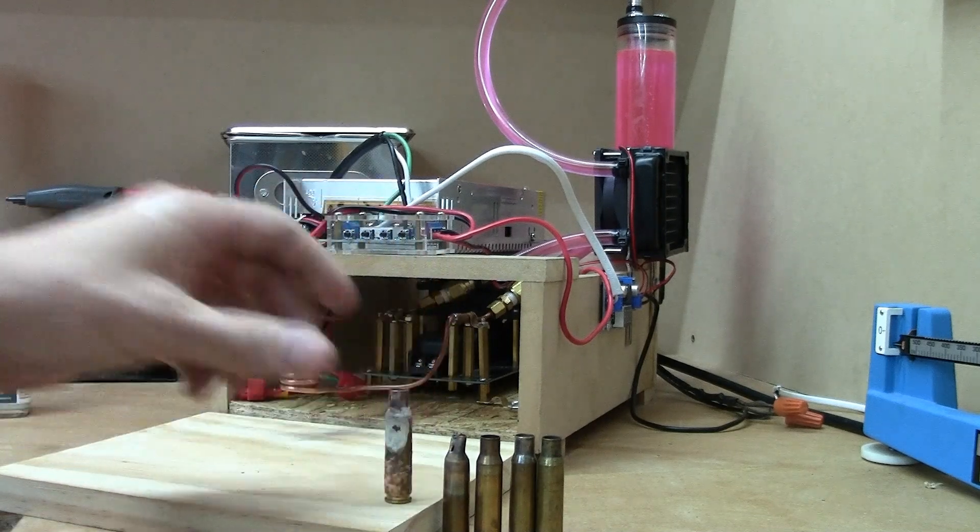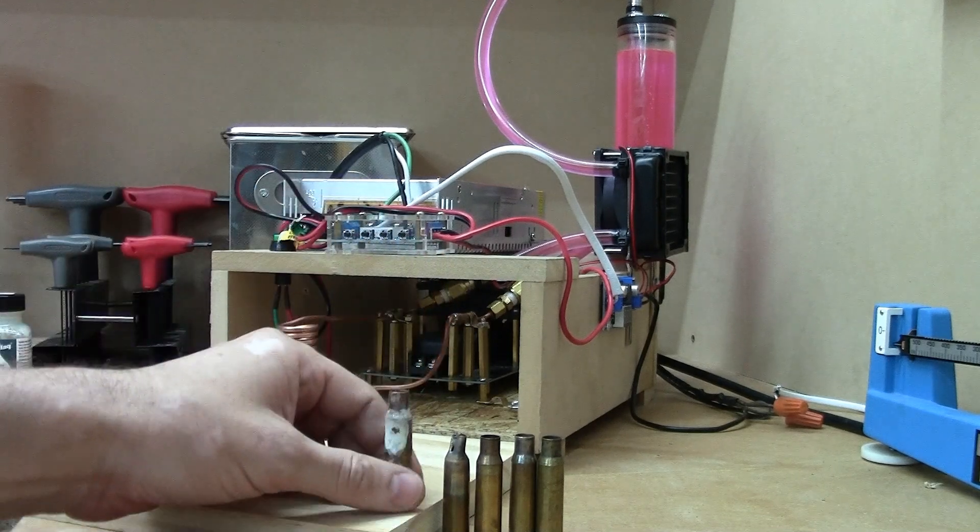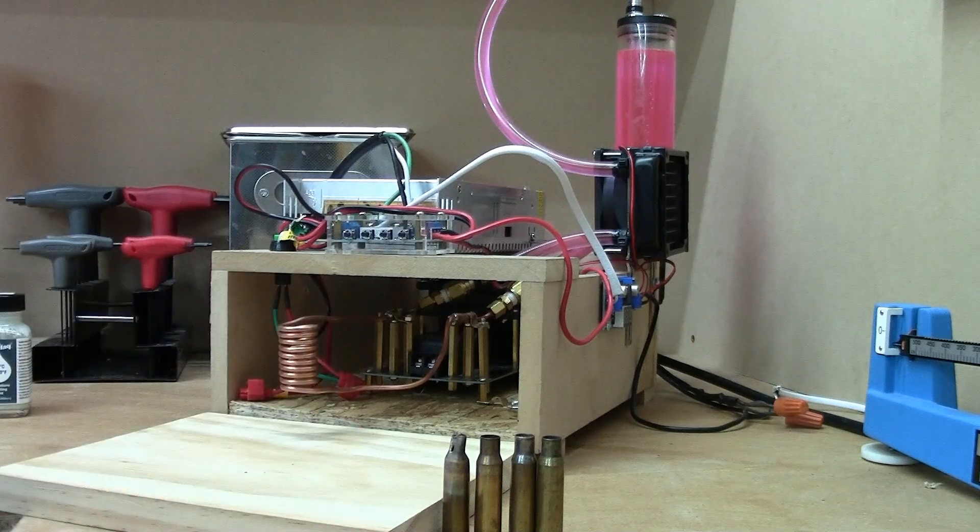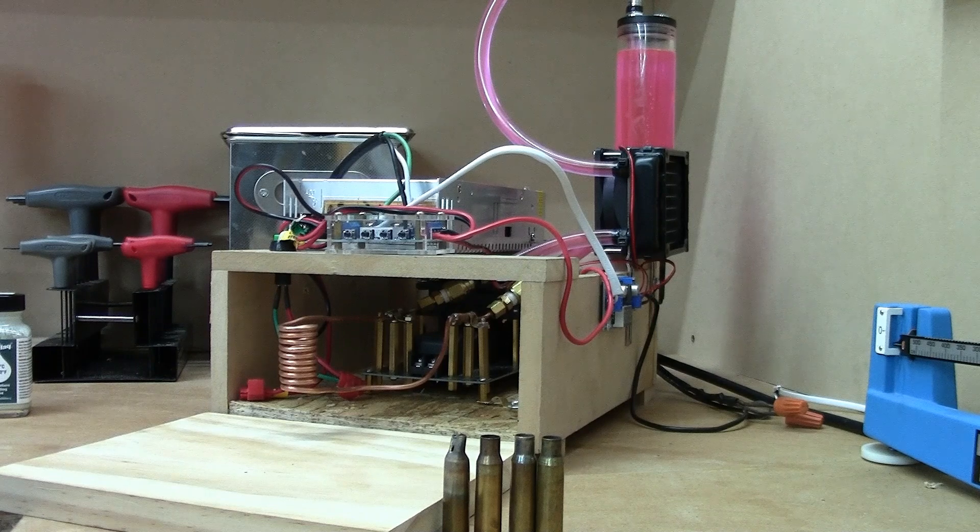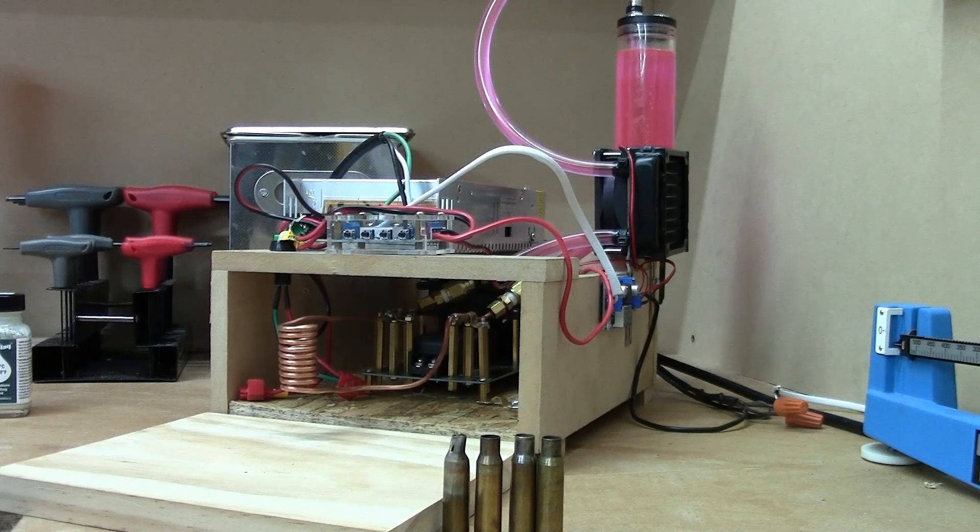So what you're going to do is you're going to use a case like this with your Tempilaq on it to set your times. Each case is going to be different thickness by brand. You're going to get more consistency out of brands like Lapua.